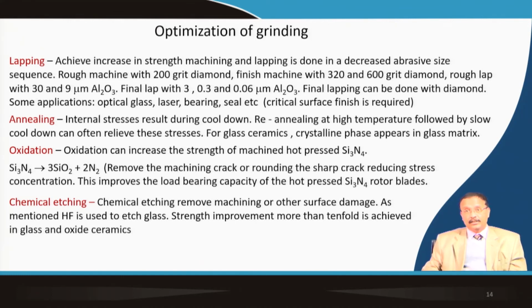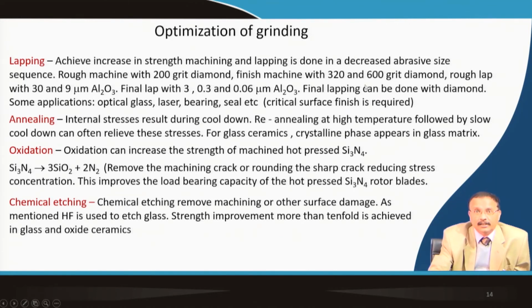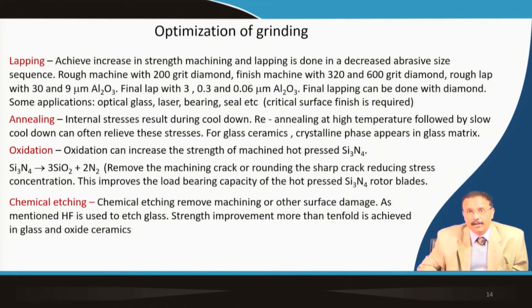Then oxidation, sometimes it is very useful in case of silicon nitride. The surface gets oxidized to form silicon dioxide. Once this is oxidized, the machining cracks are almost filled up, or at least the sharp cracks are rounded off. So, that reduces the stress concentration and improves the load bearing capacity, and as you know, silicon nitride is used for rotor blades.